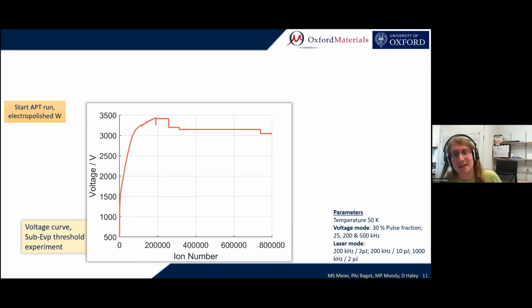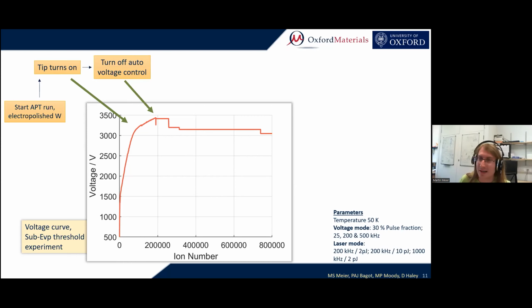Here is how these experiments work in the lab. What you see here is a voltage curve of an APT experiment with the ion sequence on the x-axis and the voltage on the y-axis. We start the APT run with an electropolished tungsten tip. The voltage increases quickly, and eventually the evaporation kicks in, the tip turns on, and the voltage ramps up a bit more slowly. Once we get a nice run, we stop the auto voltage control algorithm, and this causes the voltage to go constant. And then we come in and manually decrease the voltage until the evaporation of tungsten completely stops.